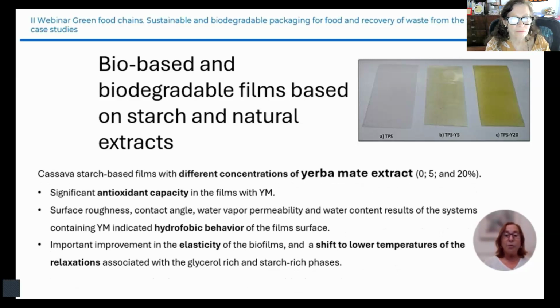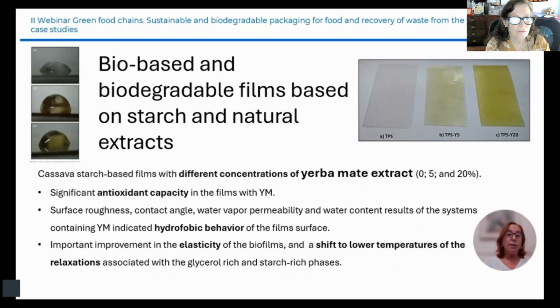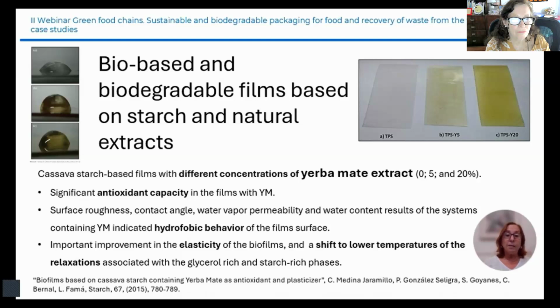from the incorporation of the extracts, and the surface of the films was hydrophobic as revealed from surface roughness, contact angle, water vapor permeability, and water content results. We also found important improvements in the elasticity of the films and a shift to lower temperatures of the transitions associated with the glycerol-rich and starch-rich phases.